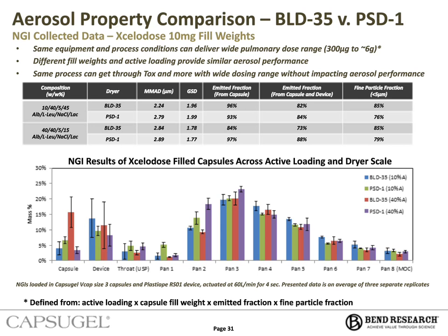So slide 31 is kind of the culmination of all of the spray drying and filling results. So what we have here is basically the 10 mg fill weights we filled with an Xcelodose system across the different spray dryer scales and active loading, so the 10 and 40%. And so again, we're seeing very similar emitted fractions and fine particle fractions, and the deposition profiles in the graph below are very similar. So this is pretty unique in that the same equipment and process conditions can deliver a very wide pulmonary dose range.